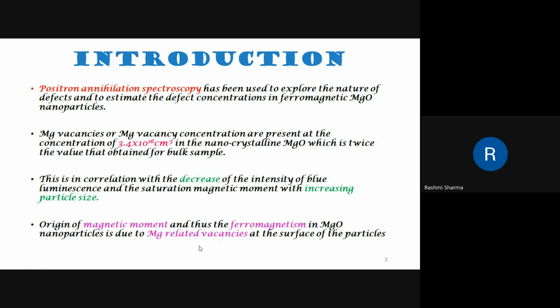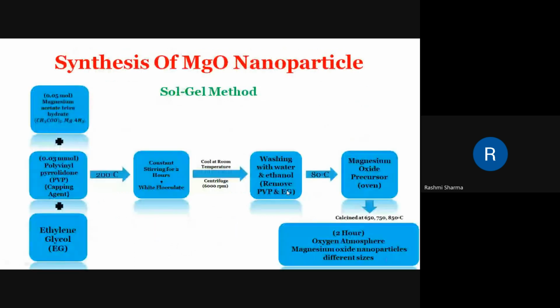So here, now we will discuss how magnesium oxide nanoparticles are synthesized. This method is called the sol-gel method. In this method, 0.05 mole of magnesium acetate tetrahydrate and 0.03 millimole of polyvinyl pyrrolidone, which is used as a capping agent, and ethylene glycol were mixed. This mixture was refluxed at 200 degrees Celsius with constant stirring for 2 hours to get a white flocculate.